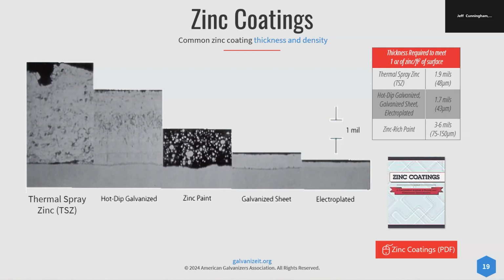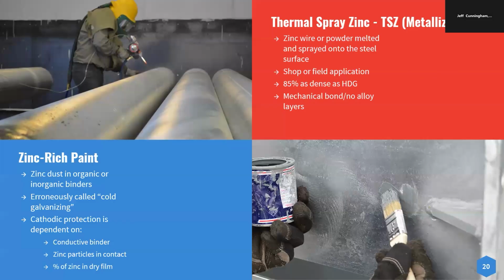You'll notice thermal zinc spray and hot dip galvanizing are going to be the thickest. But hot dip galvanizing is going to be the most dense because it's actually a metallurgical bond that's fused together. Zinc thermal spray, or metallizing, is once again a mechanical bond. It's just going to sit on top. It's only about 85% as dense as hot dip galvanized steel. All right, so we'll go into these just a little bit more so you can tell the differences.